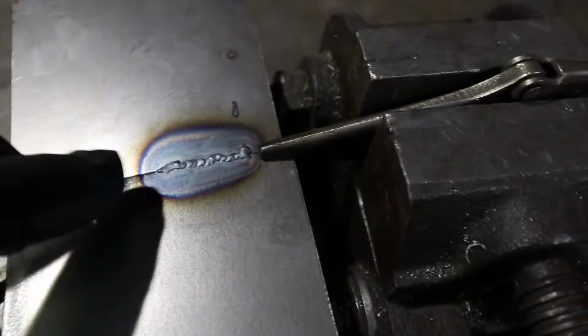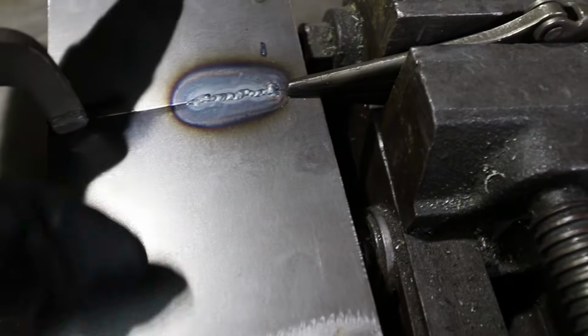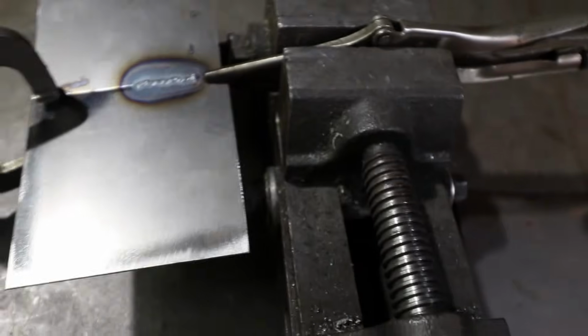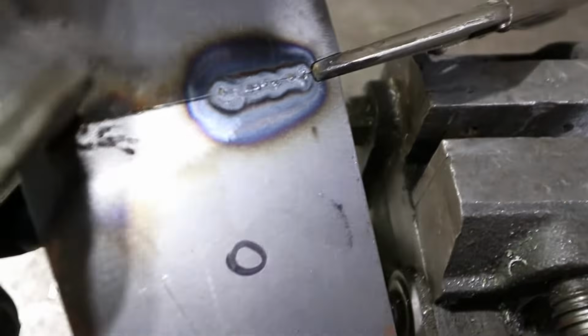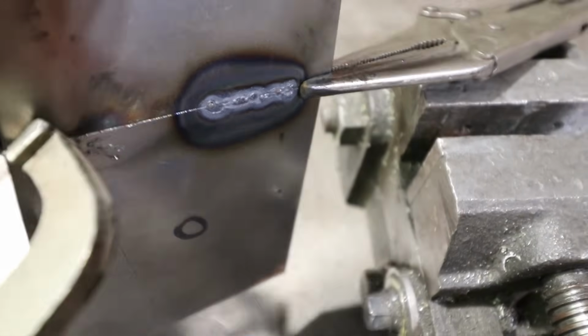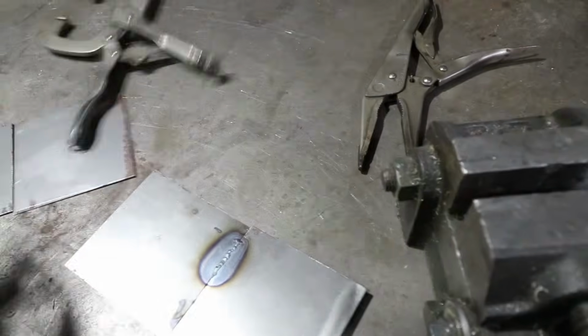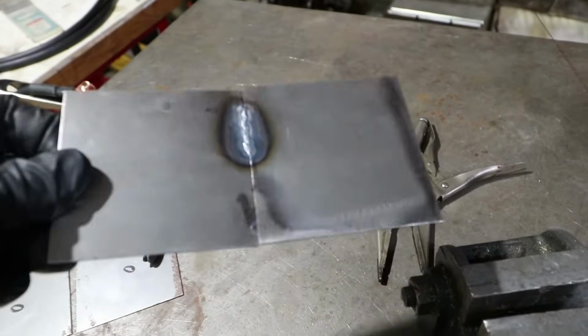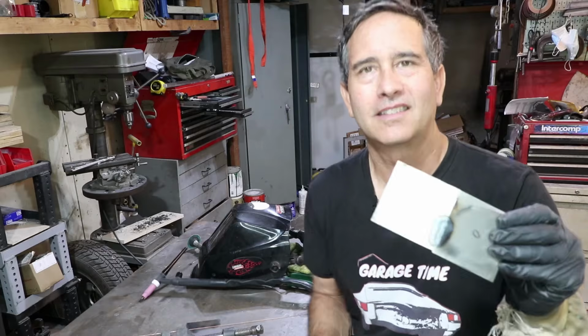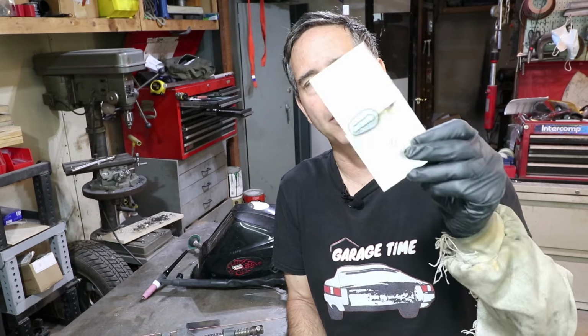Okay, and what happened, as soon as I started welding, it pulls the metal together, which is kind of a nice thing. And if you look at the back side, you know, it's welded all the way through. And it does shrink the metal, so it pulls it in tighter. And if I unclamp it, you can see it's already distorted just a little bit. I just picked this up after welding it. It's still not that hot, even though they're small pieces.